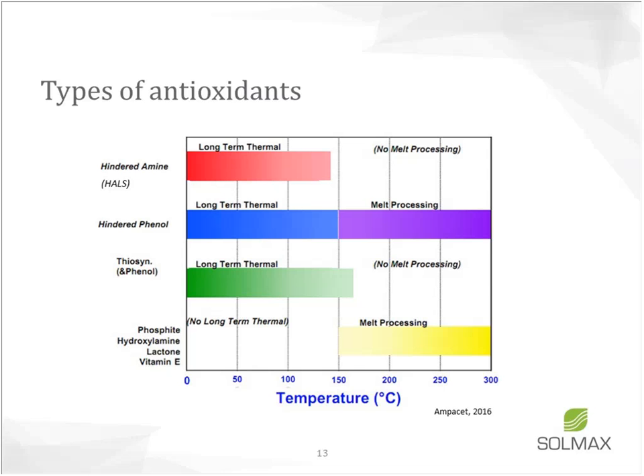There are different types of antioxidants that can be put in the geomembrane, and all react differently. The compatibility of a given antioxidant — you can't say one is better than another. An antioxidant reacts differently with different resins, and I don't just mean polyethylene versus polypropylene — even two HDPE resins from two different suppliers will react differently with a given antioxidant. So it's very important to understand there's no universally right or wrong answer in antioxidants; packages are developed for specific resins.